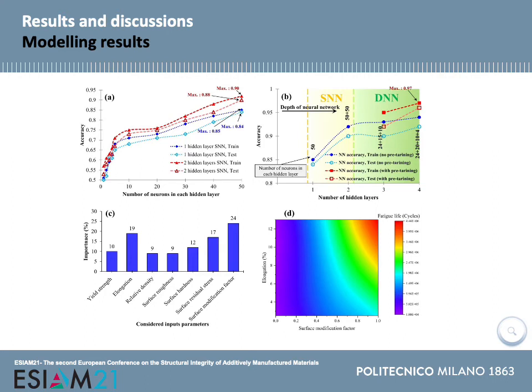In order to apply parametric analysis, the parameters that have the highest ranks based on our sensitivity analysis were considered: surface modification factor and elongation in terms of fatigue life. It can be observed that by increasing the surface modification factor from 0, which is related to the as-built, 0.5 to the shot peened, and 1 to the electrochemically polished sample, and also by increasing the elongation, which means increasing the ductility, for example by applying heat treatment, the highest fatigue life can be obtained, and it shows that these two parameters are the most important ones. This parametric analysis can also be obtained for other parameters, but in this study we only investigated the most important parameters.